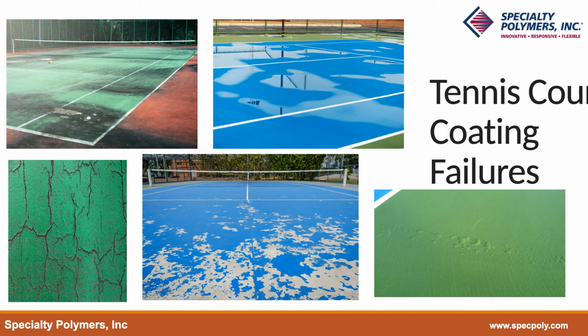There are several types of failure which are possible on tennis courts. In freshly applied coatings, it's possible to get blistering if the film is exposed to water, or if there's moisture under the film from the lack of a vapor barrier. The puddling of water on the surface is considered a major problem.